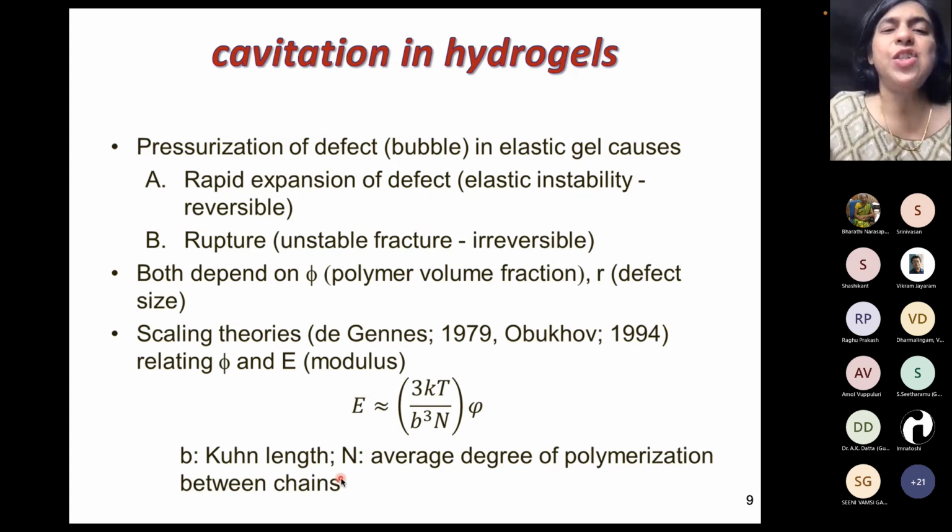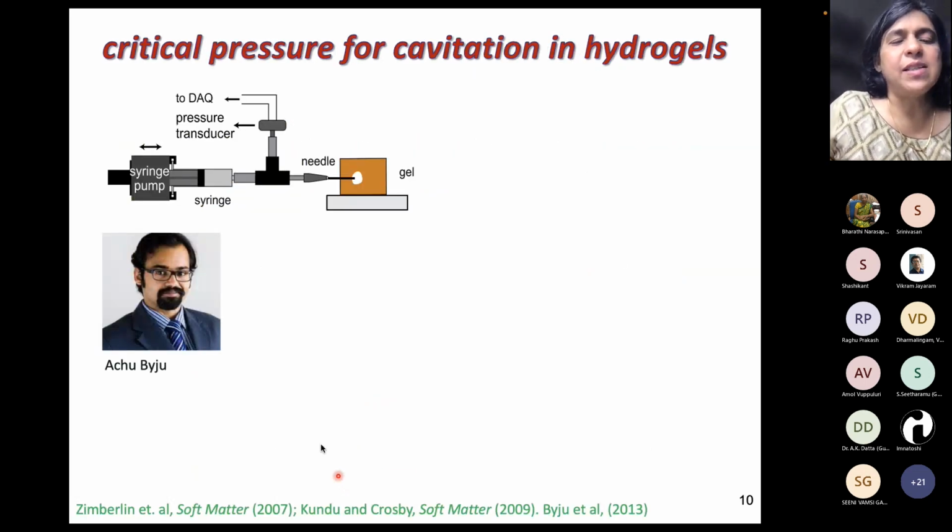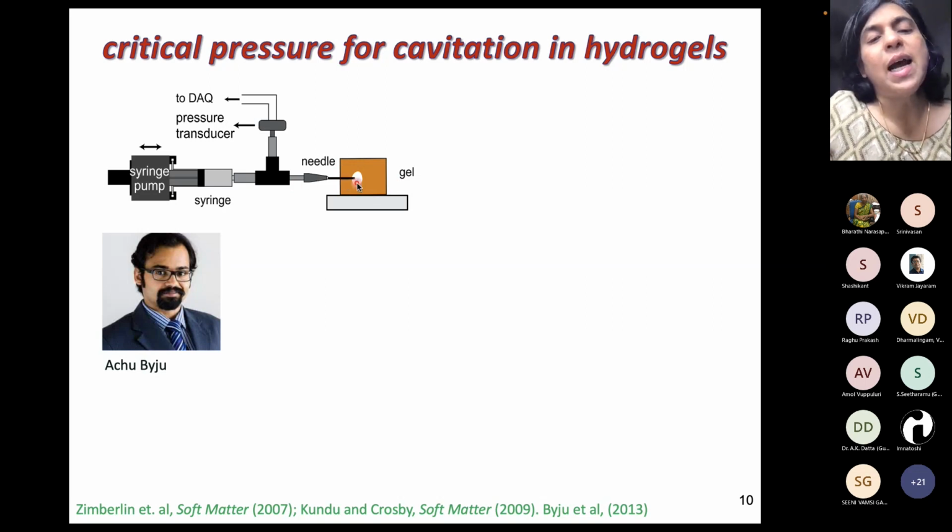And what we found in literature was this very nice technique called cavitation rheology. So the idea is, I think I should show first this slide. So the idea is simple. This orange-shaped blob is our gel. If we introduce a needle, and you can introduce needles of various bores, and these are of blunted tips, we are only looking at what happens ahead of this needle. So this is thought of as a crack tip of various sizes that you can start in the material. And we inflate this